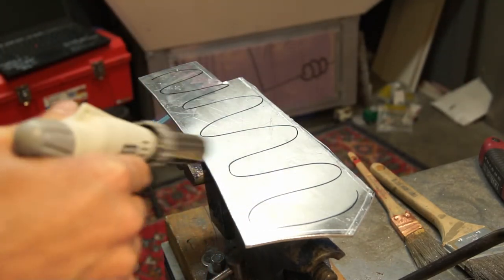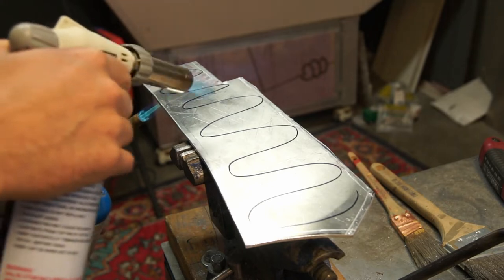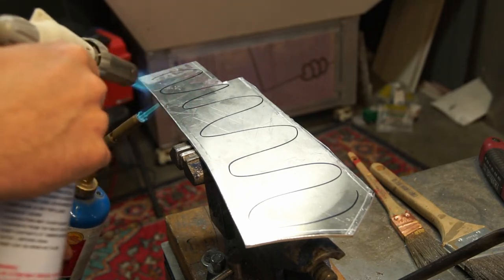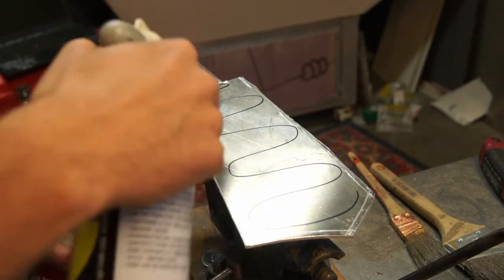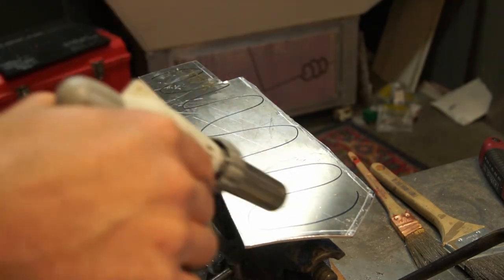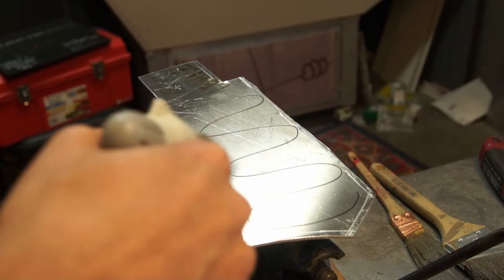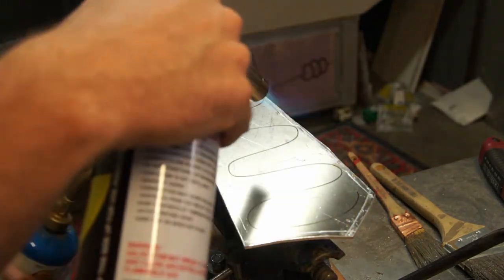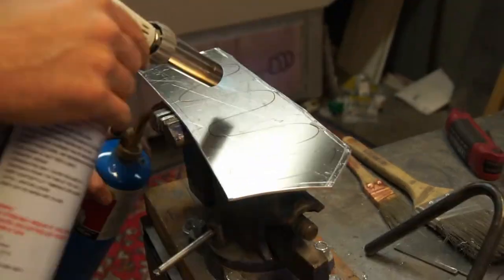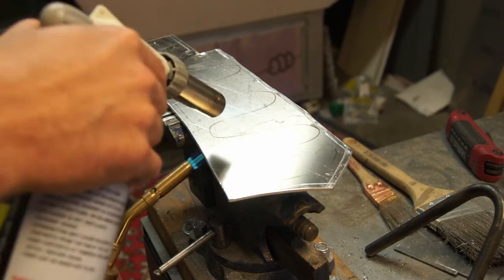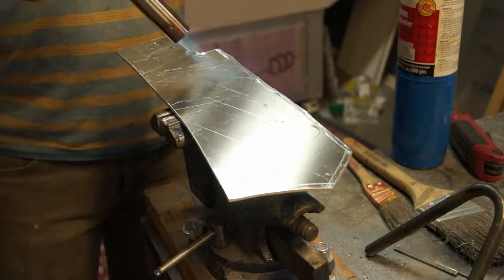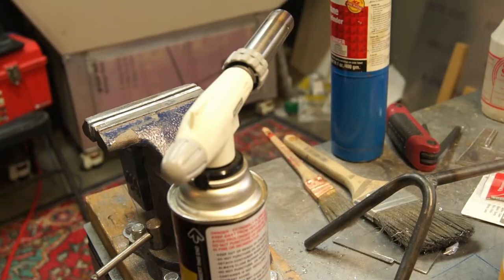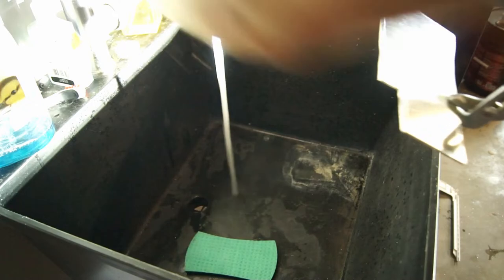Now we're heating up the aluminum, so we're going to do something called annealing. I've drawn on with Sharpie there onto the material. I got this from an episode of Adam Savage's show with Terry English. In order to anneal it, you got to bring it up to a certain temperature, and the proper temperature is until the marker disappears.